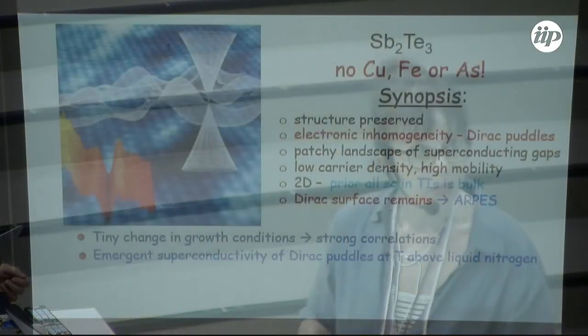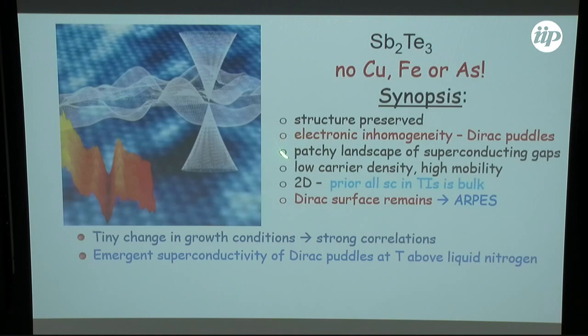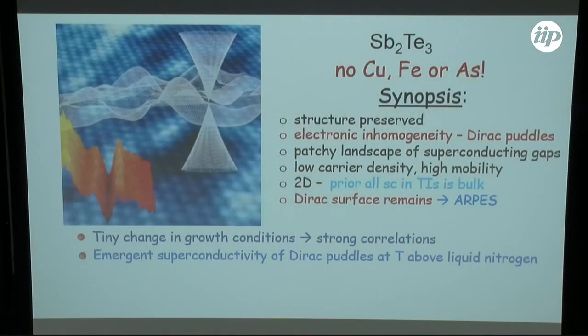What we found is the presence of Dirac puddles, which is not new. People have seen Dirac puddles before in STM, and we find that as well. And we find from STM a patchy landscape of superconducting gaps where some of the gaps were of the order of 25 millielectron volts, very high. And there is quite a wide distribution of these gaps. We also found that the carrier density in the superconducting state on the surface actually is lowered. Remember, if you've seen the data with copper doping of bismuth selenium or other materials, once the system is doped to become superconducting, you actually increase electron density or charge density.